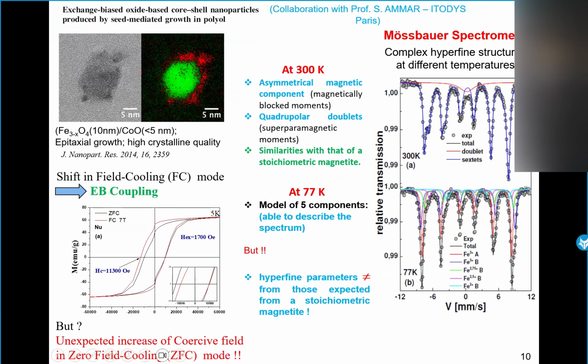We performed the Mössbauer spectrometry at different temperatures, and the different spectra show complex hyperfine structures. For example, at room temperature, we observe a mixing between doublets and sextets with a broadened line, so a mixing between blocked and unblocked magnetic moments. For the sextet lines, we observe some similarities with magnetite, presented for example by Jean-Marc previously, but we don't observe the same percentage of octahedral and tetrahedral sites. At first, we can guess that our structure is formed of magnetite surrounded by maghemite.